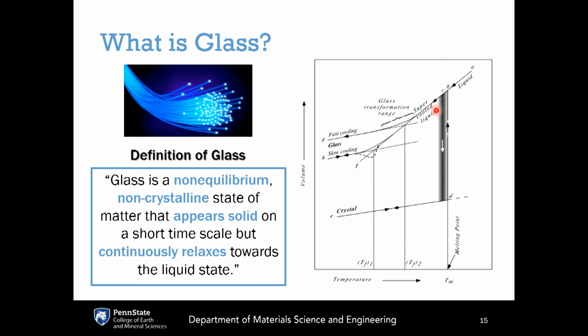A supercooled liquid is just any liquid that's cooled below its normal freezing point. From a thermodynamic point of view, this is not the stable equilibrium. The stable equilibrium is the crystal. It's what's called a metastable equilibrium, meaning it's stable on its own if it's unperturbed, but given a large enough perturbation, it can undergo a first-order thermodynamic phase transition and find a state with a lower Gibbs free energy,